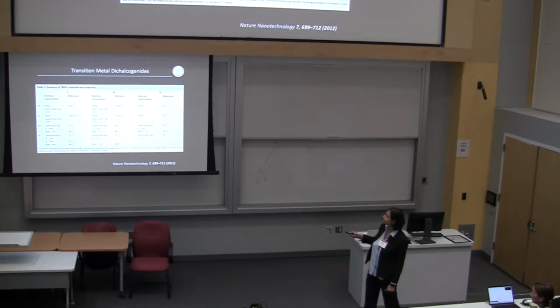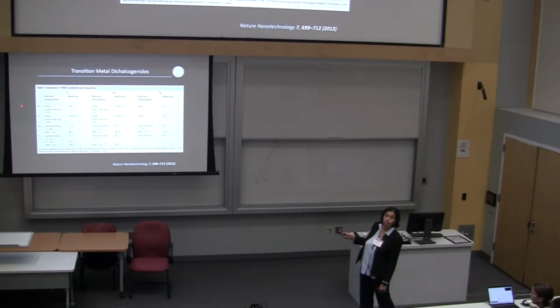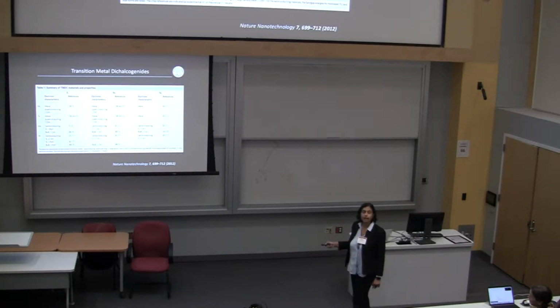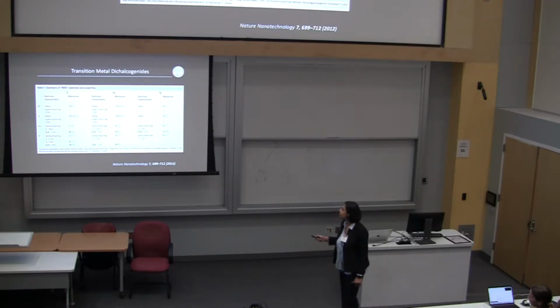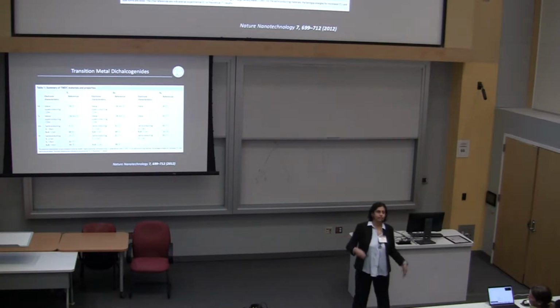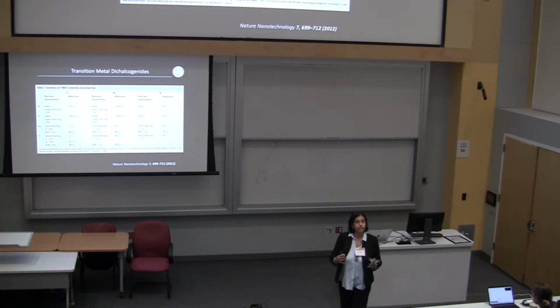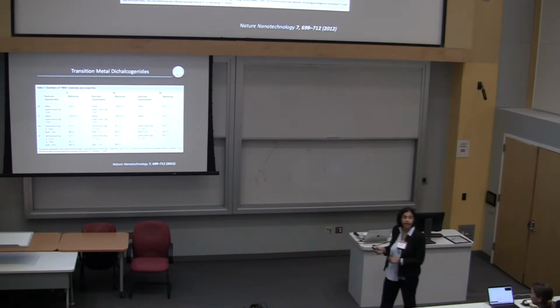So all of these, niobium diselenide, you know, is a superconductor. Tantalum disulfide is a superconductor. It also has a CDW. This is a Mott insulator. Molybdenum ditelluride is a Weyl semimetal. Tungsten ditelluride, it is really interesting. It's a Weyl system if you add something to it, but also in the monolayer form, it has topological properties and is superconducting.